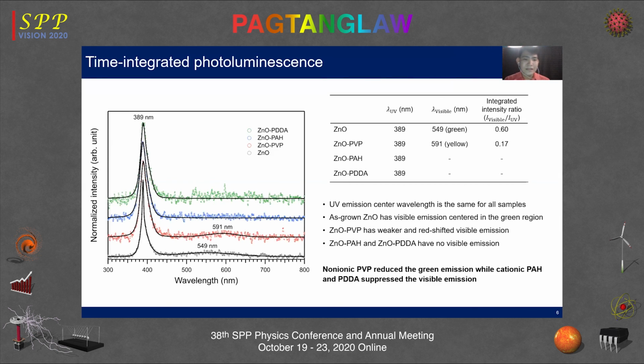On the other hand, for the case of PDDA and PAH, the visible emission is completely quenched, and it can be due to the adsorption of PAH and PDDA on the ZnO surface, since the ZnO surface is negatively charged in an aqueous solution. And one piece of literature proposed that this adsorbed polyelectrolyte on a ZnO surface can interact with surface defects, reducing the surface screening and trapping of carriers.